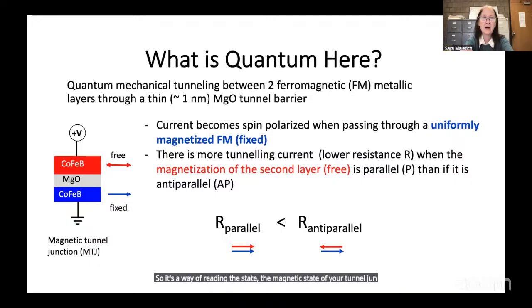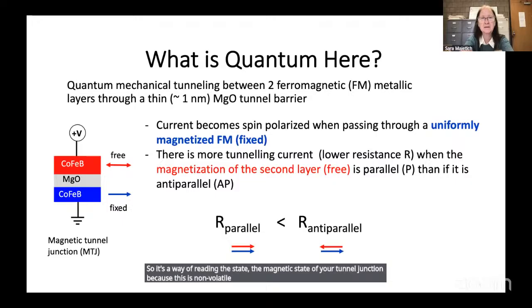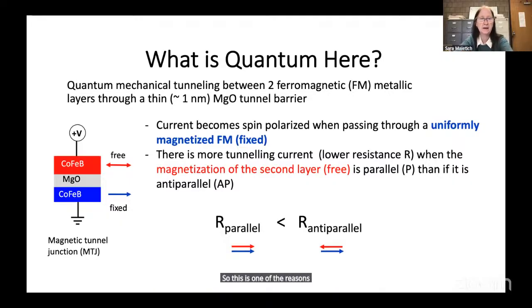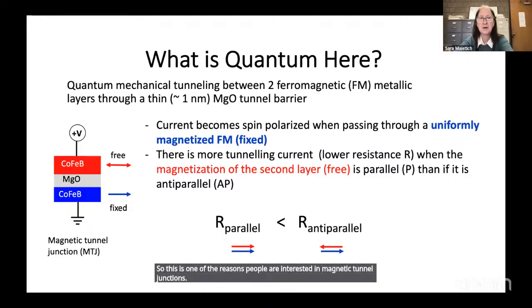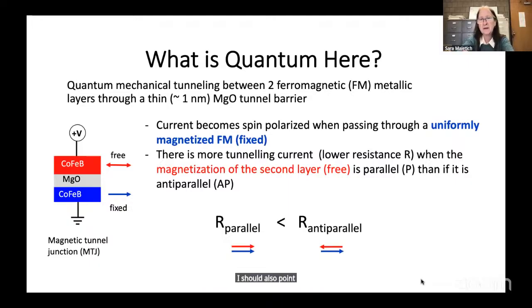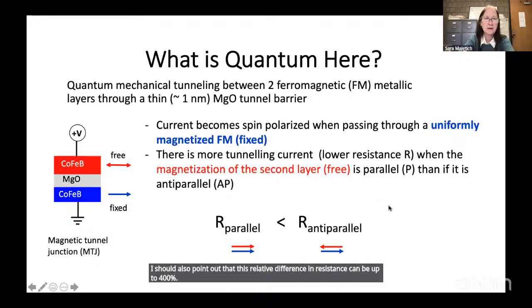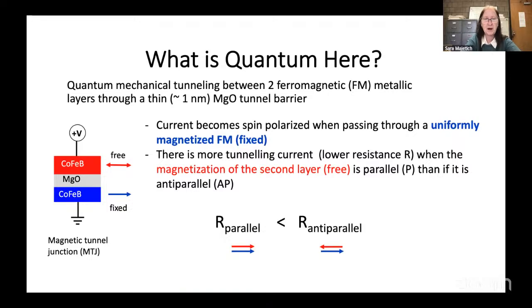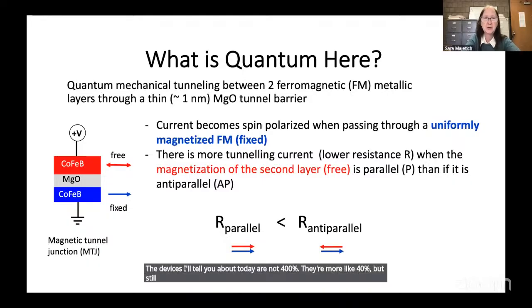Because this is non-volatile, it takes no energy to store it and very low energy to read its state. So this is one of the reasons people are interested in magnetic tunnel junctions. I should also point out that this relative difference in resistance can be up to 400%. The devices I'll tell you about today are not 400%, they're more like 40%, but still the signal to noise ratio is good enough to use in devices.